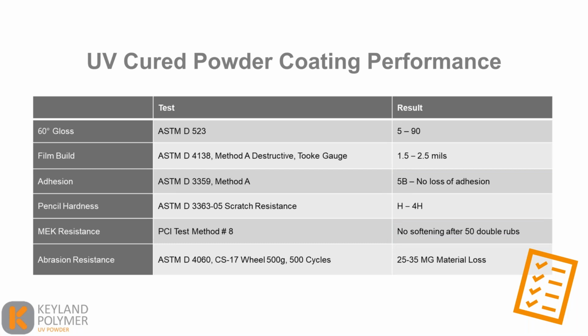So these are some typical performance properties that we would expect to see on a UV curable powder coat: a typical gloss range, as well as our film build of 1.5 to 2.5 mils, ideally a 5B adhesion, pencil hardness somewhere between H and 4H, and we do not want to see any softening at 50 double rubs of MEK, and then obviously some good Taber abrasion resistance as well.